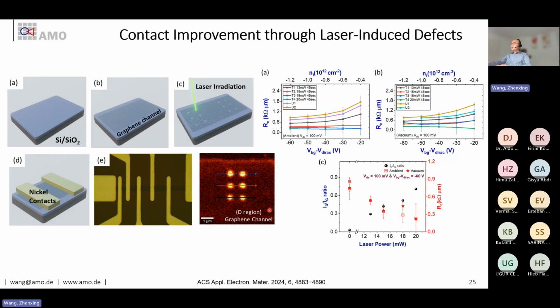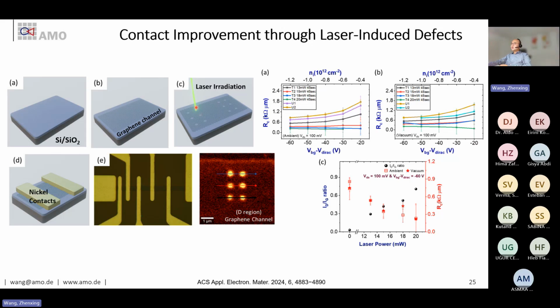So we were thinking whether it is possible to also do it directly with laser irradiation, basically to break this graphene under the contact and then make the electrodes on it. This we also tried. I think this was published last year. Then you can see this is a Raman map after the laser irradiation.